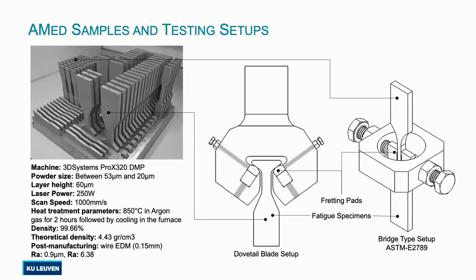I will start with the print job. So it was a very big print job, so I'm not going to talk about all the tests that we did. These are the parameters that we use, just to give you an idea that these parameters are already optimized. And I think we have launched 3-4 PhDs during the last 3, 4, 5 years in collaboration with Siemens to find the optimum parameters for this material. But some of the important results: at the end, we got 99.66% density, and also the roughness is very good.